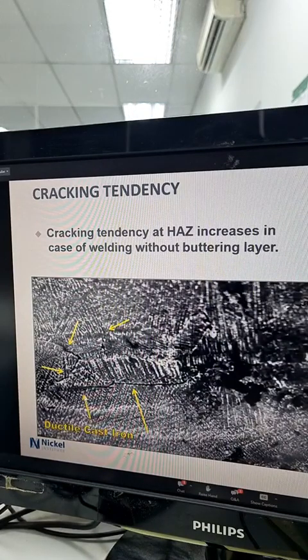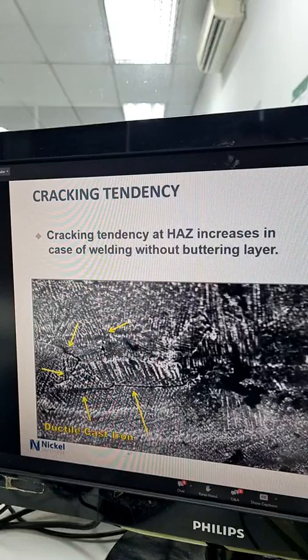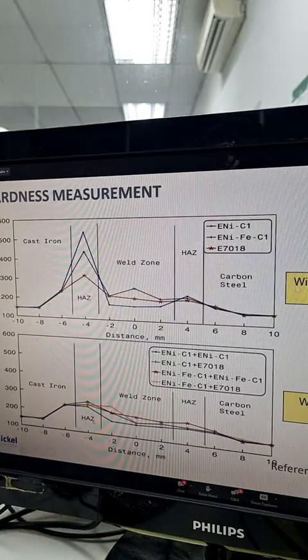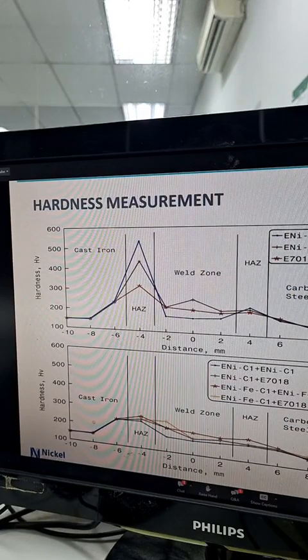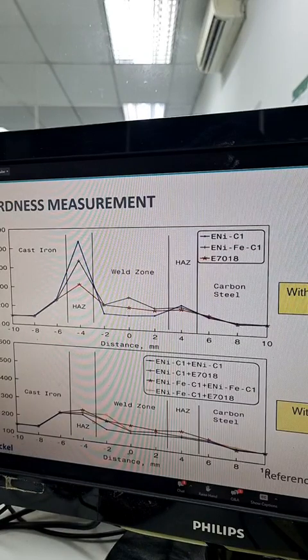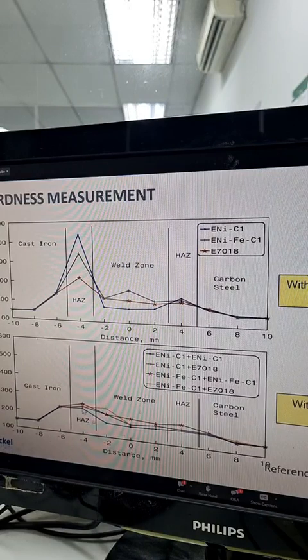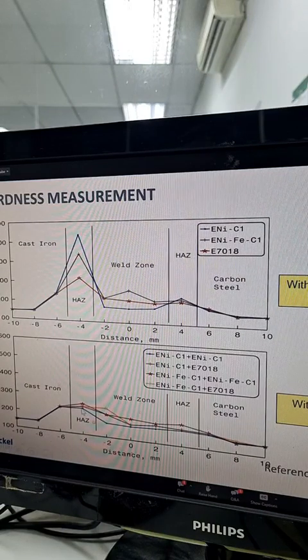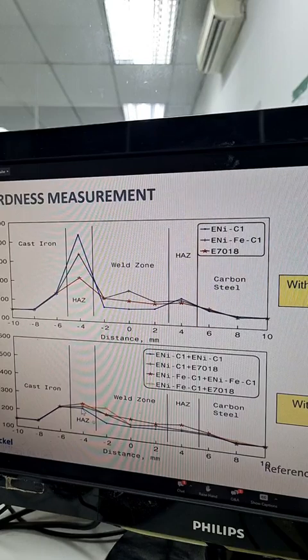What was observed was a huge crack at the HAZ when they tried welding it without a buttering layer. And you also see the hardness in the heat affected zone without a buttering layer with the different consumables like ENi-C1, ENi-Fe-C1 and 7018. The hardnesses were quite high, though it was a little less with 7018. But when a buttering layer was produced and then subsequently it was welded, the hardnesses were relatively low, and that is how you should tackle the situation.